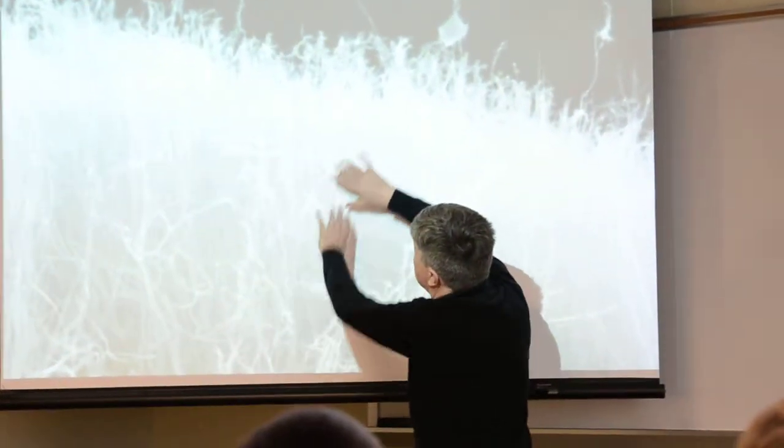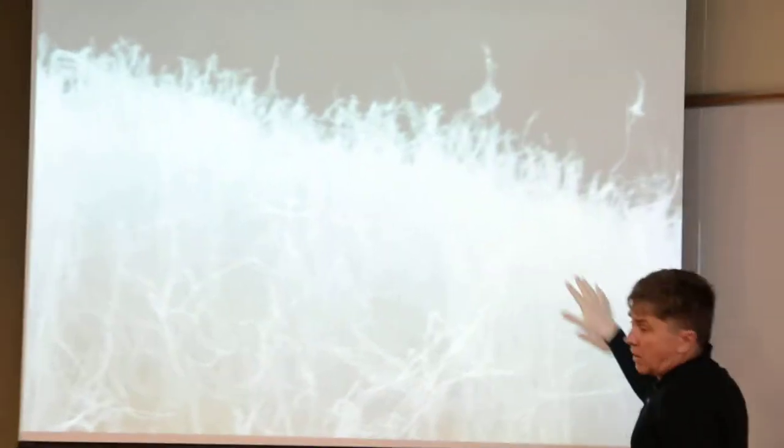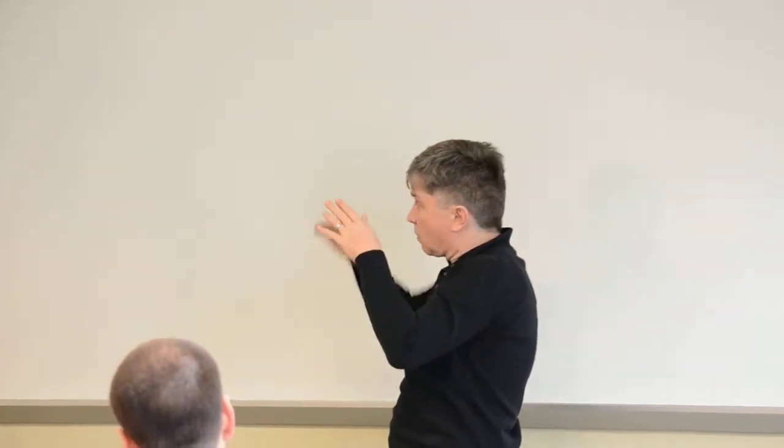Which one is going to emit? The longest one. This one will emit first, then the tiny ones down here. Eventually they're shielded by this. Now you can understand where the noise comes from. You have all these tubes, different lengths, and thousands of them emitting. That's why once you reach the top, there's flickering, noise in the current, because some of them start to burn.